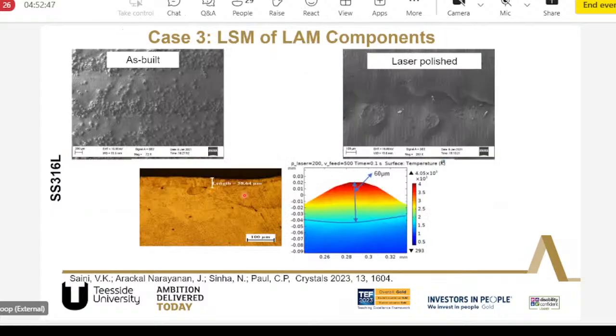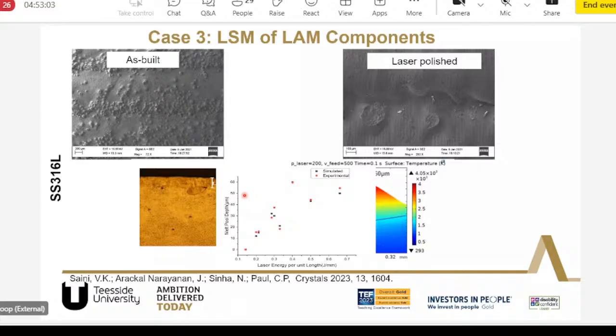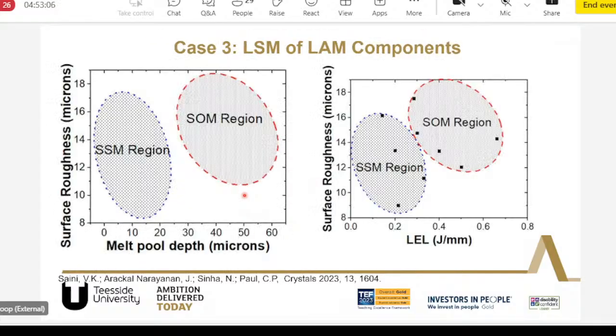Then another project that we recently did and published was on laser surface melting, which is a laser post-processing technique where we used a continuous fiber laser to polish the surface of already manufactured parts, and we could see a lot of improvement in the surface roughness. So we developed a process window where we can go for the melting. There are two different zones, surface over melting and shallow surface melting. We need to identify based on our requirements.